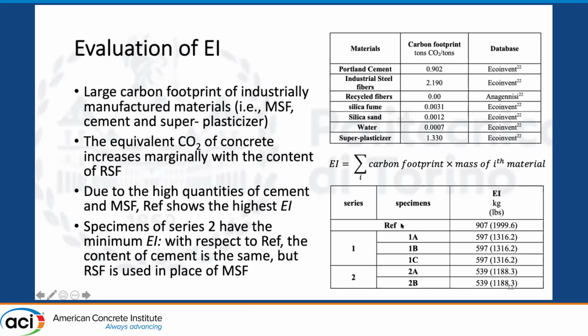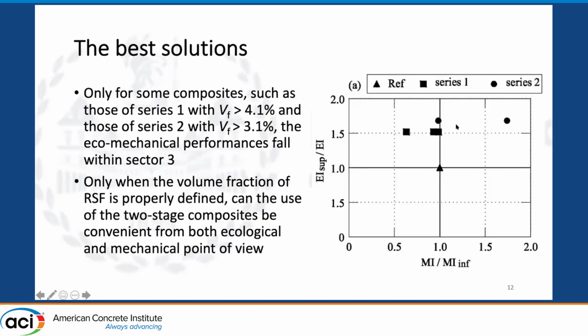Obviously, the largest impact is that of the reference system, because we are using Portland cement and industrial steel fibers. On the contrary, the lowest impact is that of series 2, because we reduced the cement with respect to reference 1, although the content of fibers is that of recycled steel fibers, so with 0 impact.